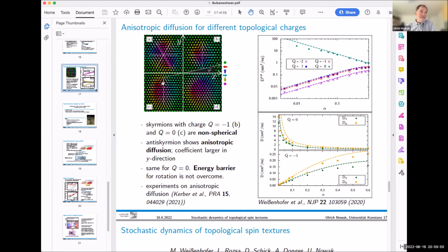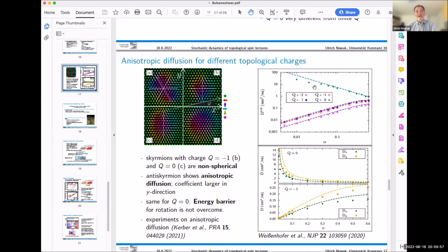Yes, I would, and I would say the same as before. Namely, the skyrmion with the topological charge 0 would probably follow this curve, which is funny. That would be a nice effect because you see they are so different. Q equals 0 should be fine, if you manage to measure that. As I said, the problem is always the defects. So in experiment they do not follow exactly this simple theory, because the defects act as energy barriers that have to be overcome, and your diffusion coefficient will not just be linear in temperature; it will be exponential with energy barriers. So it's a bit more complicated, but we would expect to see this difference in the topological charge.